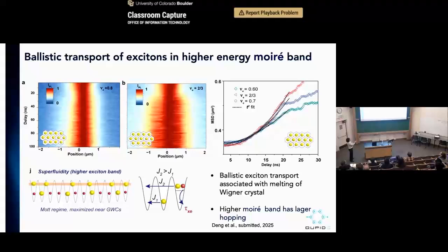And also very interestingly, if I plot the MSD as a function of time, it's no longer linear. Linear tells you it is diffusive. Now what we see is actually quadratic. And quadratic MSD comes from ballistic type of motion. Notice that the time and the speed of this ballistic motion depend on the density of the charge. It's the most enhanced at 2/3 filling, and if you go beyond that or below that, it reduces.